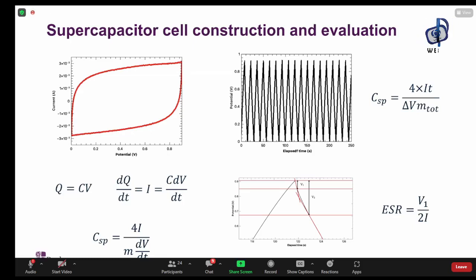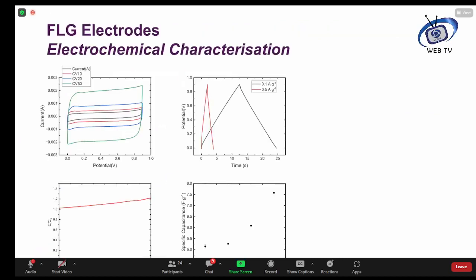So we first produced a series of few-layer graphene samples. So electrodes consisting of graphene alone. And as you can see from the cyclic voltammetry, they are very rectangular indeed, which indicates extremely good electric double layer capacitor behavior. Likewise, the charging and discharging curves are extremely linear. And we find with cycle number, not that the specific capacitance decreases, it in fact increases. So the more we cycle these materials, the better they get, not the worse. So that's the good news.